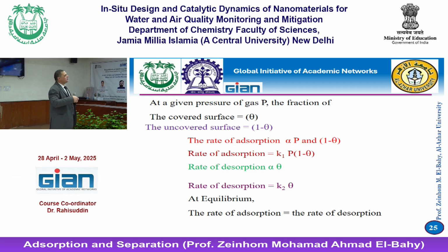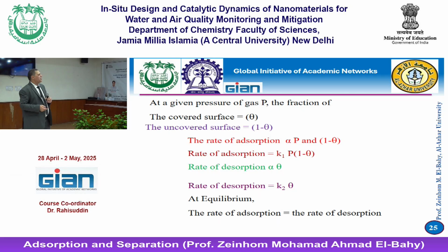Then the rate of adsorption depends on P and 1 minus theta. Of course, we will remove the proportionality sign and it equals K1 P (1 minus theta). This is the rate of adsorption. And the rate of desorption is proportional to theta, so the rate of desorption equals K2 times theta. At dynamic equilibrium, the rate of adsorption is the same as the rate of desorption.